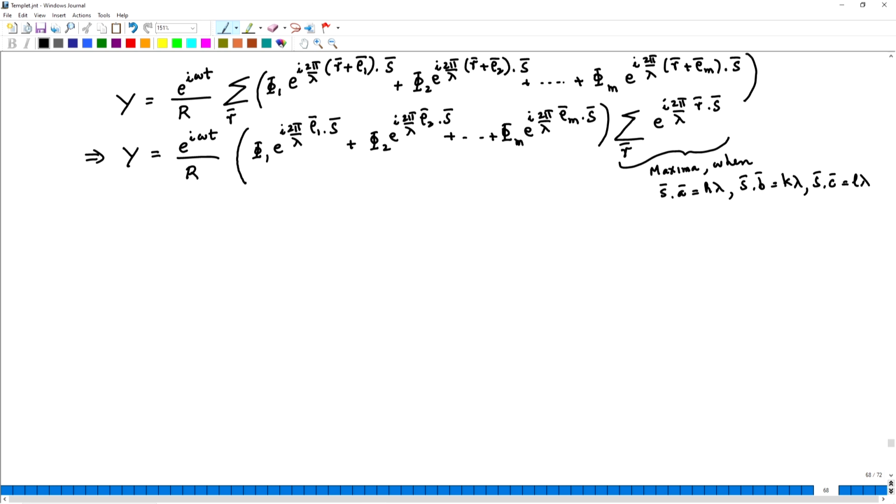So, when Laue conditions are satisfied, or we can also say when the Bragg condition is satisfied, then we want to analyze this term, because then the intensity will be governed by the magnitude of this term, which has now individual atoms inside a unit cell. Let me call this term capital A, which is also called the structure amplitude.